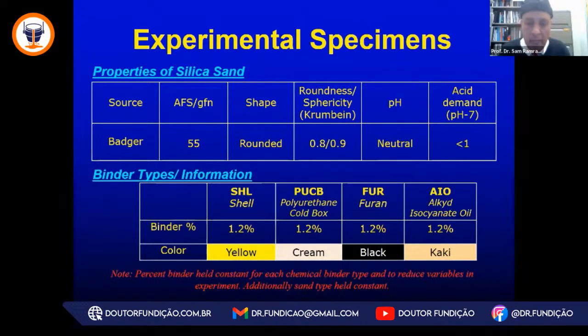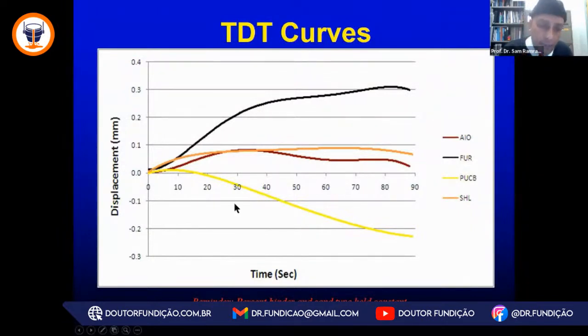All of the sands were held constant, and so too was the test temperature, head pressure during the test. We just wanted to compare what would happen. Again, this will not be an indictment on any of the chemical binder systems. It is to make a point. And the point is, if I show the displacement on the x-axis and time as a function of temperature for a typical axial or longitudinal thermal distortion curve, what you are seeing here for these sand binder systems that I just mentioned, the alkyd isocyanate oil in brown, the furan system in black, the urethane cold box system in yellow, and the shell system in a tan color.